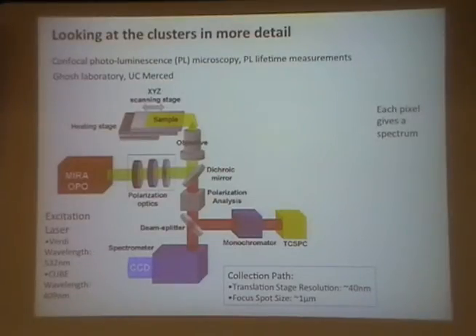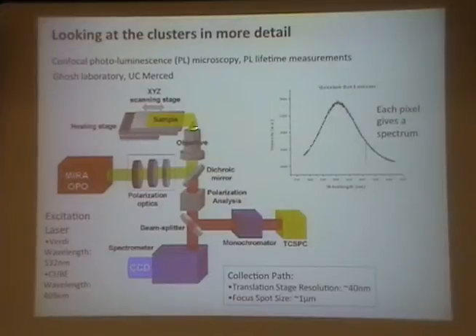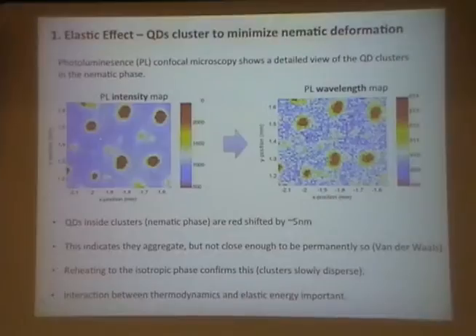And we can do different excitation wavelengths, particularly 532 is a good one for us to use. The quantum dots have quite a broad absorption, but then they emit in a narrow range. So it's quite easy for us to excite the quantum dot and then get their emission. And we can also do pulsed excitation for the ultra-fast lifetime measurement. Here we can see an example. When we scan and collect an image on the CCD, each pixel has a spectrum associated with it. Then we can look at that spectrum and see the peak, the maximum wavelength of emission. You can also do a lot more analysis on the spectral shape and so on, but I'm not going to talk about that now.